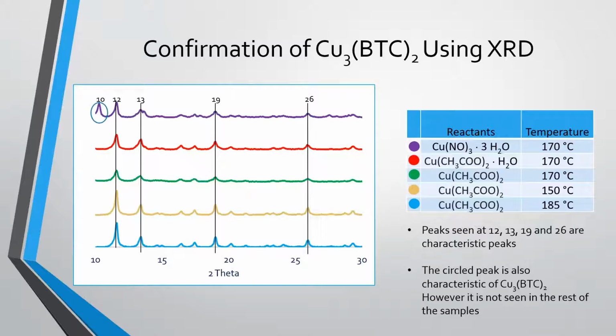When comparing these, all of our samples had the peaks at 12, 13, 19, and 26. However, copper nitrate was the only one to have the characteristic band at 10. Again, this is likely to be disrupted due to the water of hydration that could be disrupting the copper bonding.